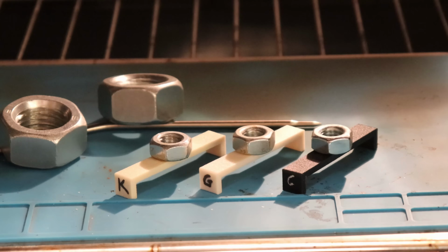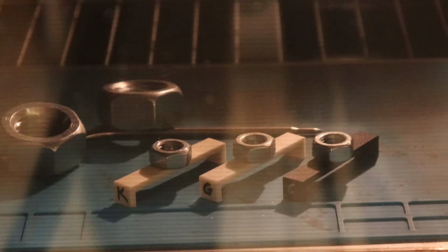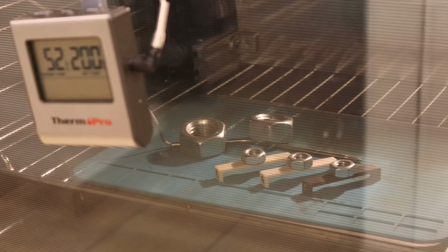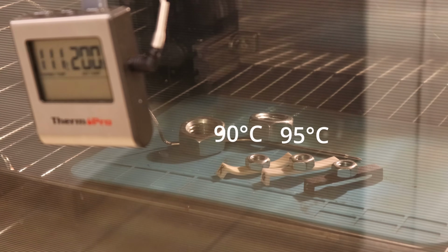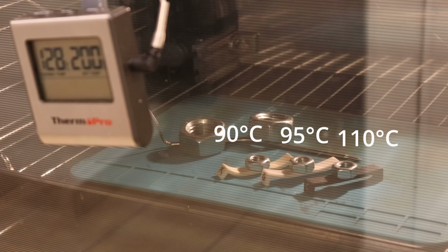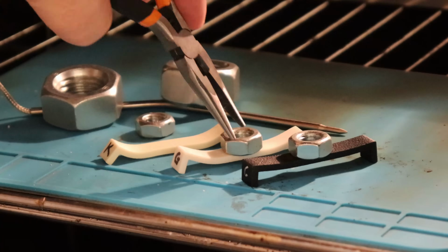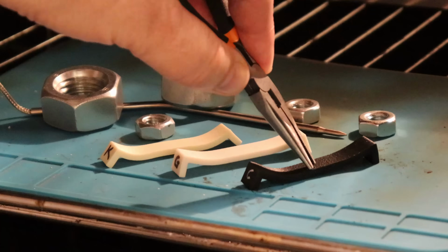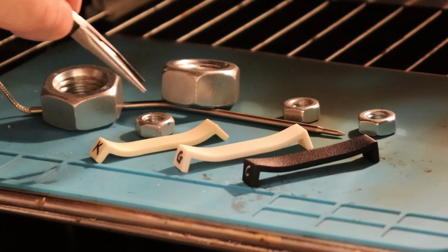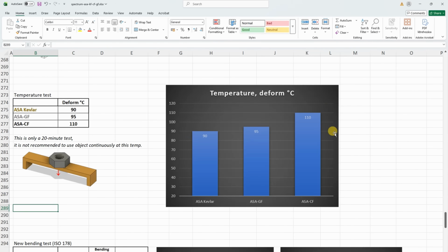Temperature test in the oven. I was trying to record the temperature of the first noticeable deformation, with an M10 nut as a small load, and the first one which started to deform was the Kevlar, then glass fiber, and the last one the carbon fiber version. At 130 degrees I stopped the experiment, and I just wanted to check how hard or soft they are. Carbon fiber version quite hard, but these two are very soft. It is typical that fibers increase the temperature resistance, but in this case only with the carbon fiber version. The other two, Kevlar and glass fiber, have similar temperature resistance like no-fiber ASA.